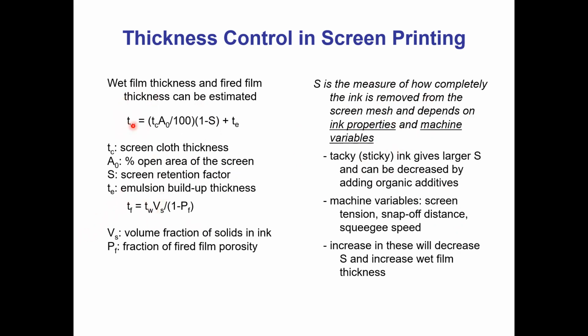And the wet thickness is related to the final fired thickness by this relationship, where Vs is the volume of the solid fraction in the ink, which is something that we know. Something that we don't quite know without doing experiment is the fraction of fired film porosity. What is the percentage of porosity in the fired film? That's something we have to do on our film by doing microscopy. We fire the film, do microscopy, and figure out the percent or fraction of film porosity.